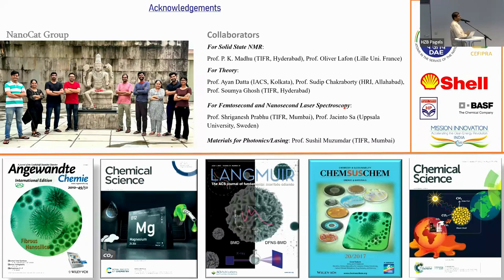The reason why we chose nickel is because catalysis is a very complicated thing, as you know. You want to have the photon, you want to generate the electron, you want to transfer the electron to the CO2. At the same time, you also want the CO2 to sit onto the active site where the electron is generated. And we knew that nickel is good in terms of chemically sorbing the CO2. That's why we use nickel. I think we can also use other metals. We're trying to explore that part. So that's the reason why we use nickel rather than a semiconductor.